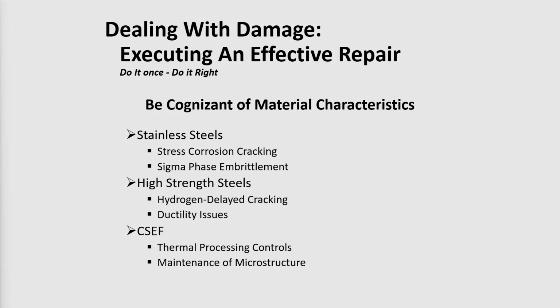And then, of course, with the creep strength-enhanced ferritic steels like grade 91, all of the thermal processing and the control of the thermal processing has got to be at a much higher level of control than even for other materials. And the microstructure must be maintained during any kind of weld repair that's carried out.